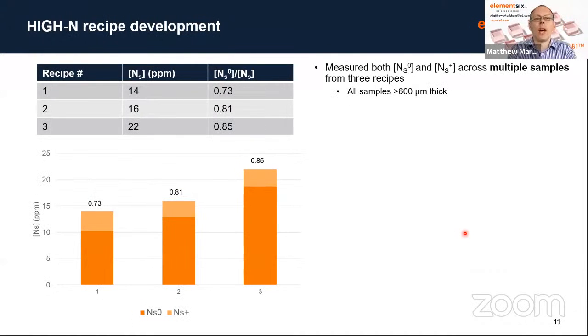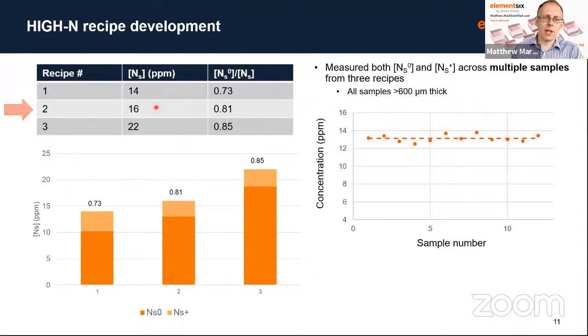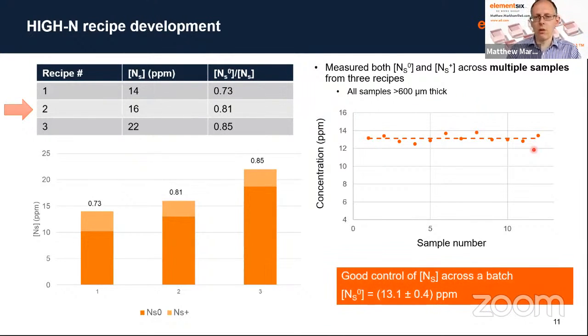We then did a more detailed study of these higher nitrogen contents, where we took 3 different recipes, measuring both the neutral and the positive charge state of the nitrogen. That's quite key, because the positive charge state means the electron from the nitrogen has gone to some other defect, which isn't the NV defect. So you want to reduce the amount of Ns+ as much as possible. We can see that in this plot and table, where by changing the conditions we're able to increase the amount of neutral nitrogen. We then selected this particular recipe because it was the target recipe for our application, and we're able to demonstrate that we can grow consistent material across a whole batch of samples. So we have very good control of nitrogen.